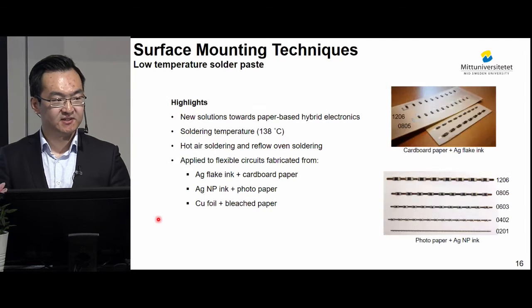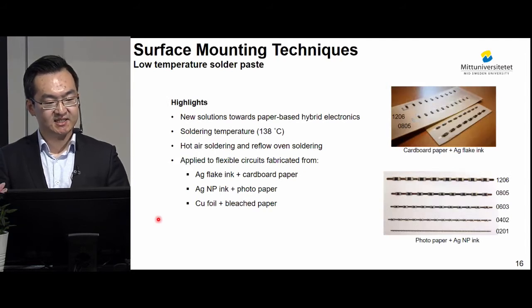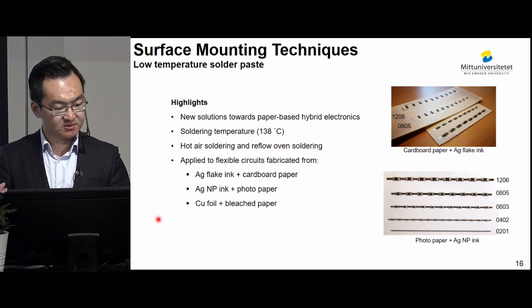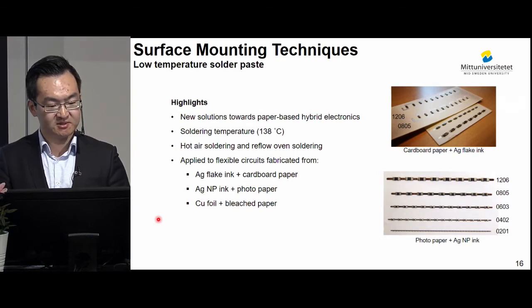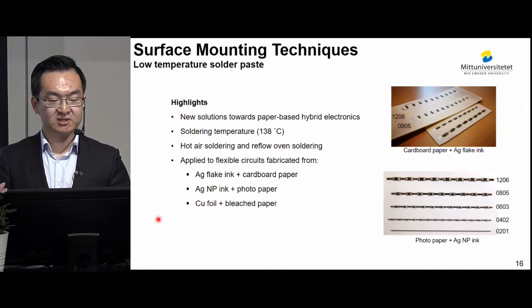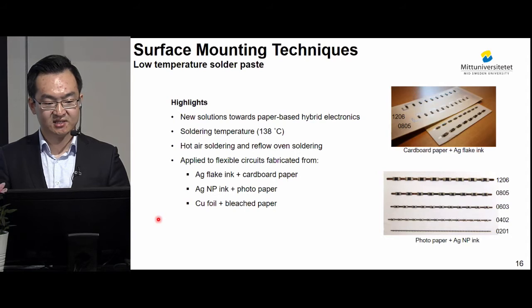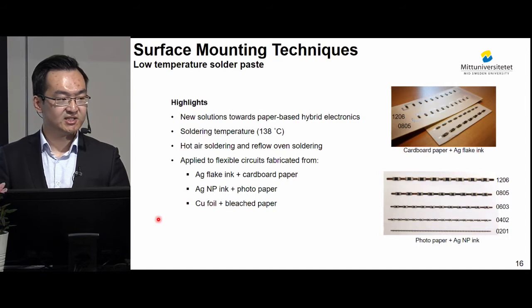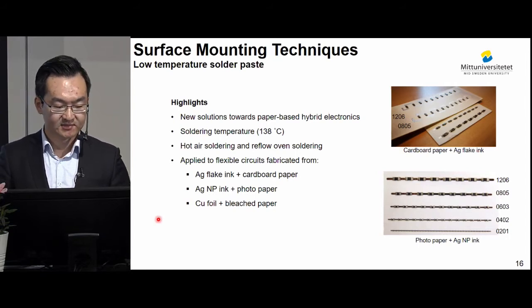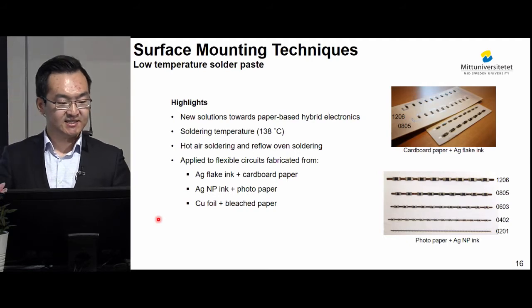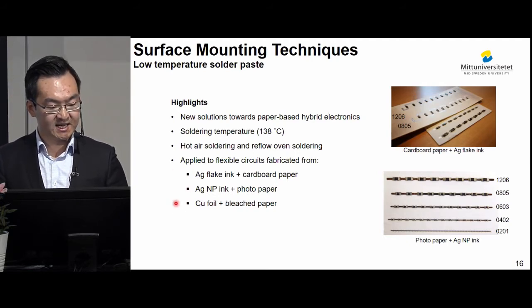With that being said, the first surface mounting technique is to use a low temperature solder paste. The reason why we developed this is because we would like to bring new solutions towards paper-based hybrid electronics and also avoid high temperature when using the traditional soldering method. The soldering was performed at a temperature of 138 degrees, and we evaluated both hot air soldering and reflow oven soldering. And we applied this technique to the following 3 types of circuits.